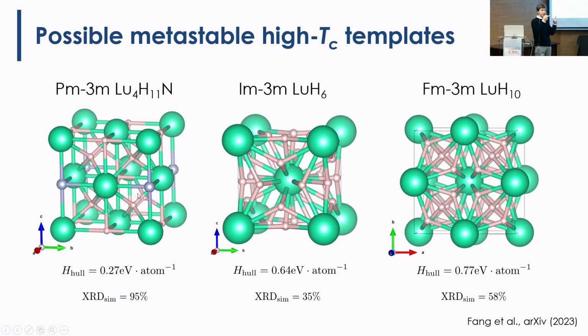the lutetium H3, but we substitute out of 4 hydrogens in the octahedral side by 1 nitrogen. So this is nitrogen. And this is a bit closer to the convex hull, but it's still very far, okay, energetically. But maybe one could say, is this metastable? Yes, no, I don't know. Here, by X-ray, this could be confused with the X-ray, because basically it's FCC and the volume is basically the same, okay?